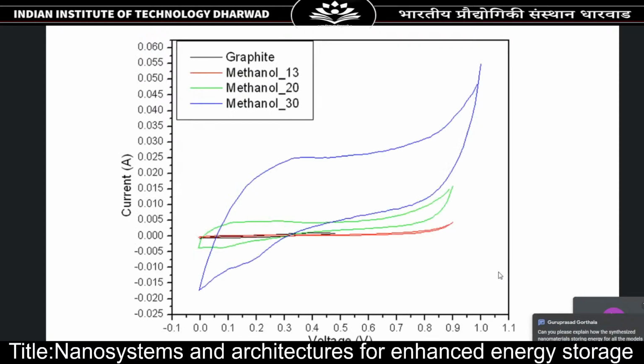And this shows the dramatic behavior in electrochemical studies. This is a CV curve. You can see that the graphite curve is almost minimal because it does not show much electrochemical response. Then the 13 hours prepared sample in methanol has an almost vanishing area under the curve. 20 hours is slightly better, but look at the 30 hours curve. It has increased dramatically. That shows that if you prepare graphene very well through exfoliation, it can be used as a very good material for energy storage.